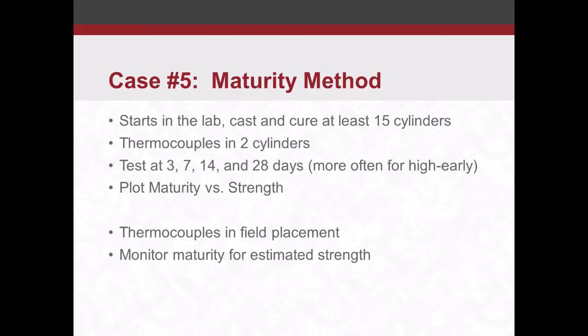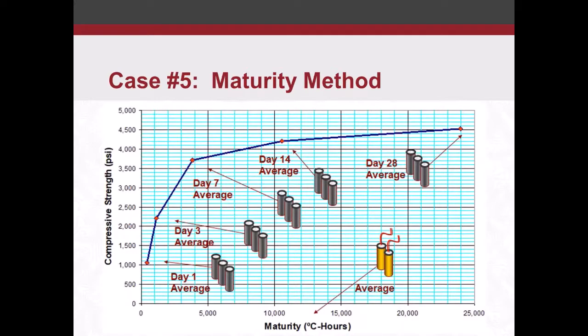And then in the field, we put the thermocouples in the field, and then we just monitor the maturity for strength in the field. Typically, we'll get a curve like this. Test cylinders at day 1, 3, 7, 14, and 28. Plot the compressive strength and the maturity. Again, our units are degree hours. So typically we get a curve like this.